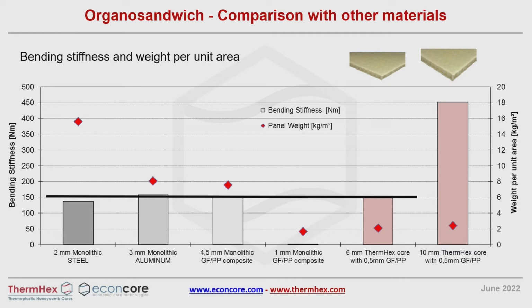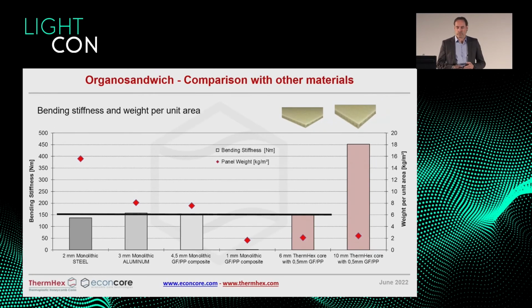So this shows with very little amount of materials you can reach a very good bending performance, and you can outperform many of the other materials. And in the last column, you see then the effect in bending stiffness of a thicker panel. If you go to 10 millimeter, then you have a much higher bending performance and only a very little increase in weight.